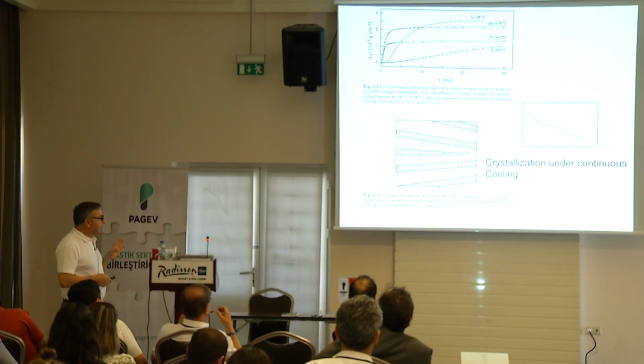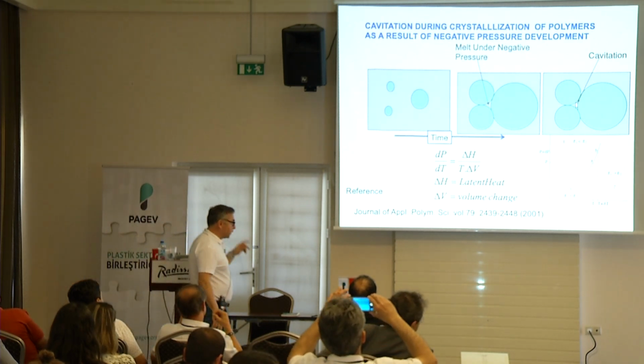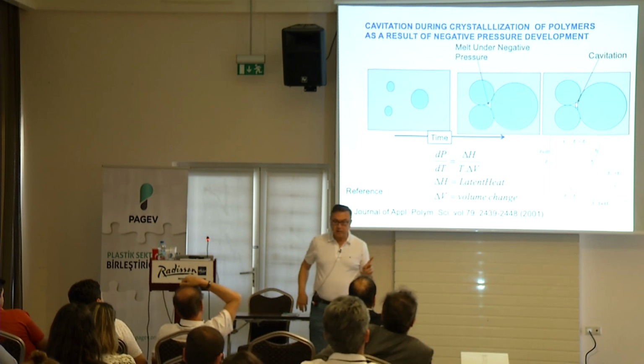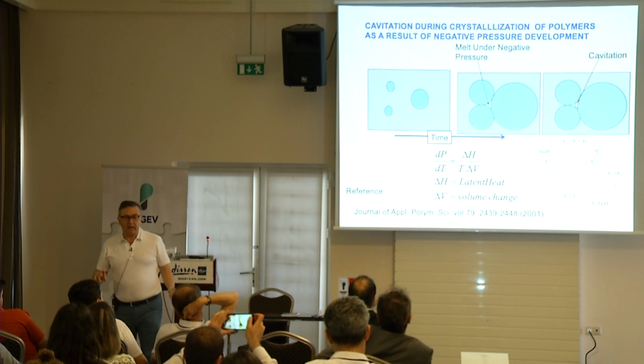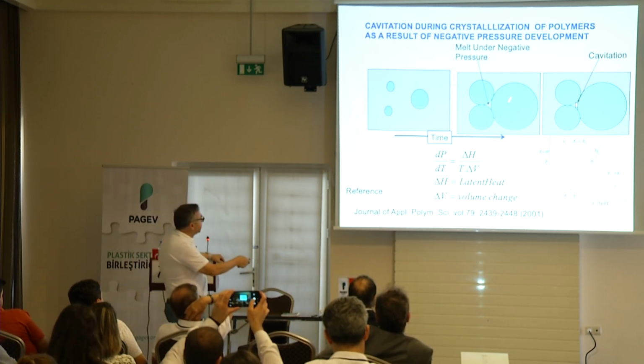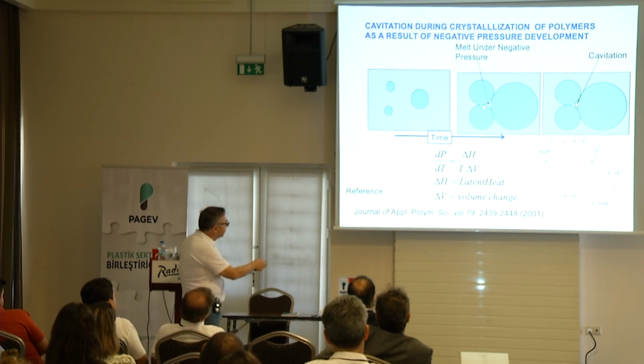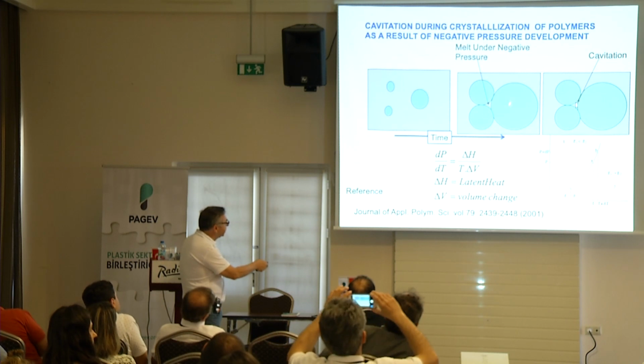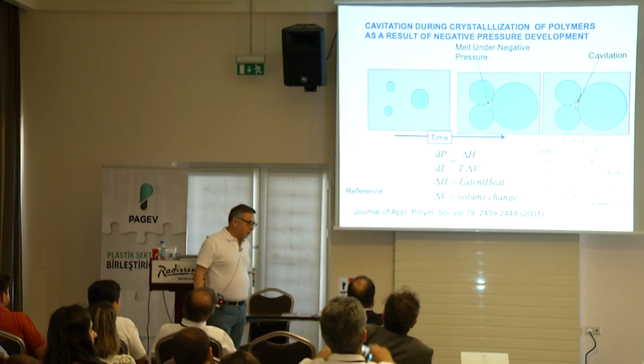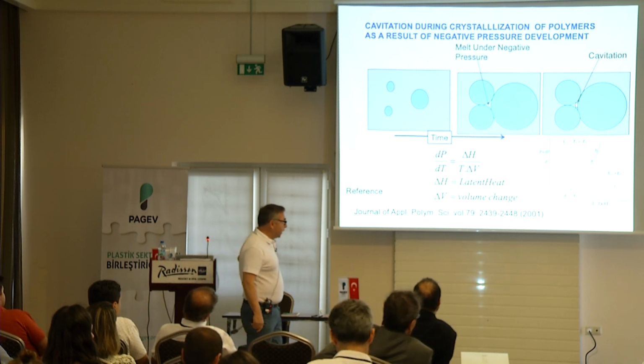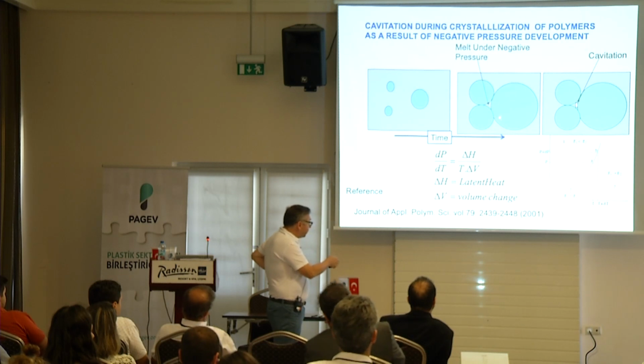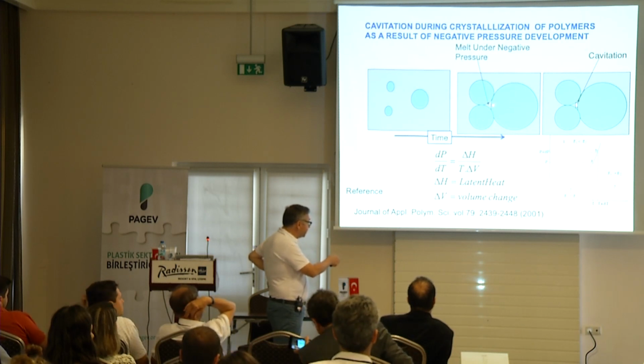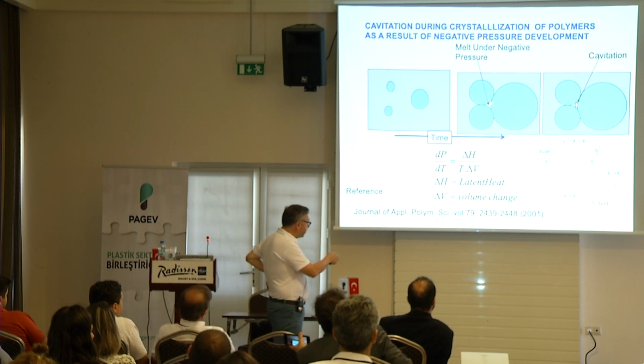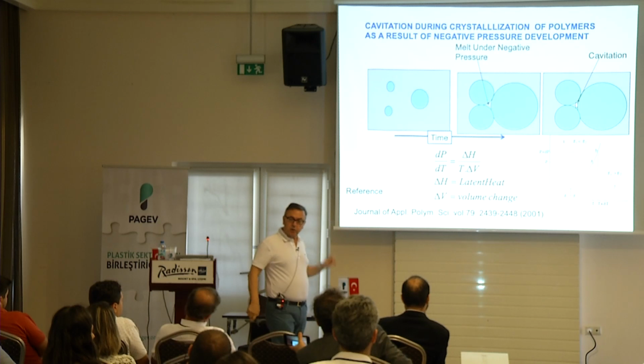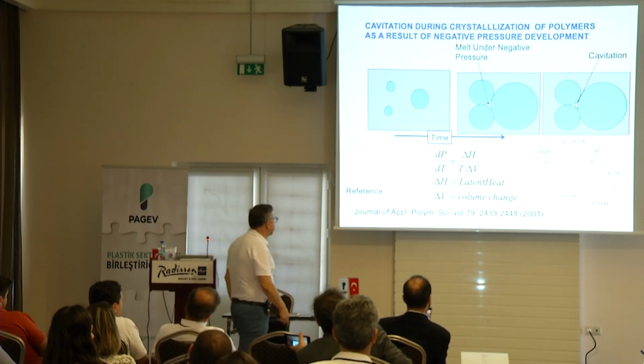Okay, so that's the important message. The other one is very practical. Most people don't appreciate this, but it does occur. When the crystals are growing and they impinge on each other, what happens at the interface where the material is not completely solidified, but is confined by the neighboring crystals? This is a very important phenomenon that most people don't appreciate because it leads to cavitation. The reason is, remember, when we convert it, this is high density, this is high density, this is high density, this is low density. So once all that material is confined and depleted, you basically rip the structure apart. You create a bubble. You actually create a void. Okay?